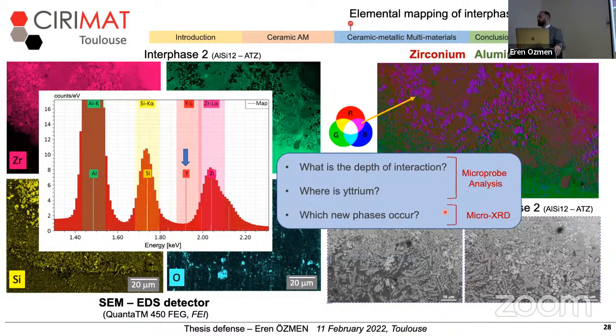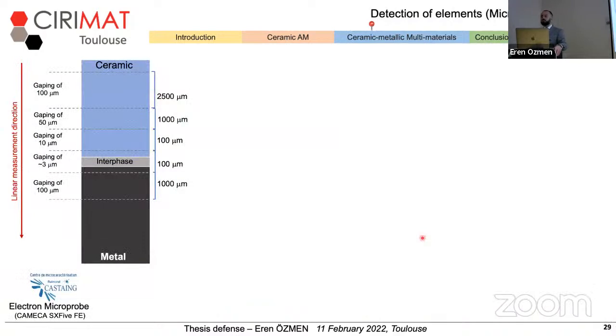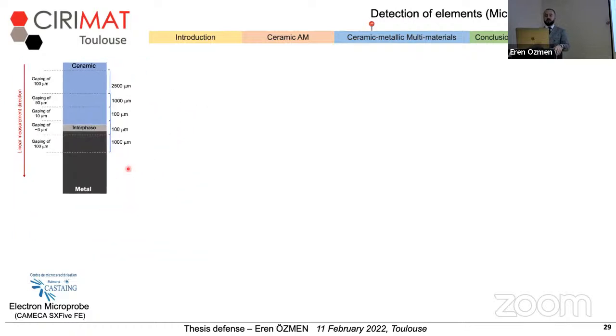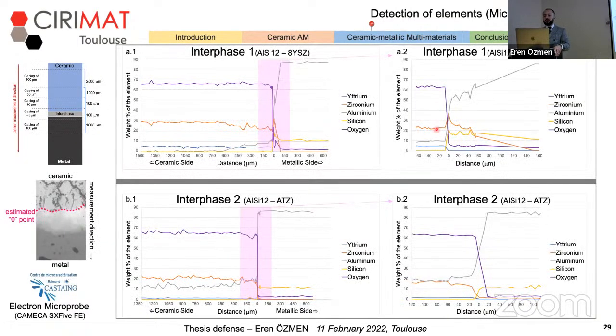To answer these 3 questions, I used 2 methods: electron microprobe analysis and micro-XRD. Electron microprobe analysis makes a point-by-point elemental analysis. I follow an experimental flow where we study the elemental composition point by point, and we reduce the gap between 2 points when we come close to the interface. So here we see the elemental distribution of 2 interfaces, the first one in the upper row and the second one in the bottom row.